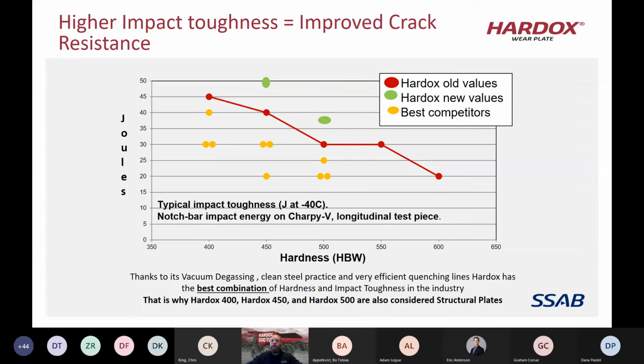So this is basically a chart showing the toughness values, or what we call the Charpy impact toughness. It shows how tough the steel is and how resistant it is to cracks. If you look at the red line, that is the old Hardox values, basically what we used to see about 5 to 10 years ago. But today, if you look at the 450 Brinell hardness, the green dot at the top, we're seeing Charpy impact toughness values of around 50 joules at minus 40 C. A lot of our closest competitors are down around 30 joules at minus 40 C. So we can see a lot better impact toughness in those applications where the plate is being put under a lot of impacts.